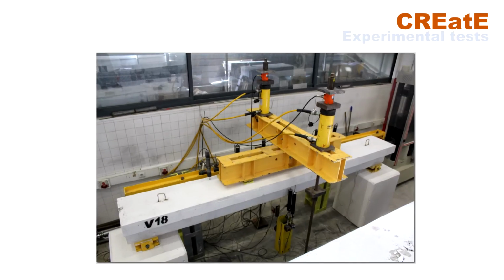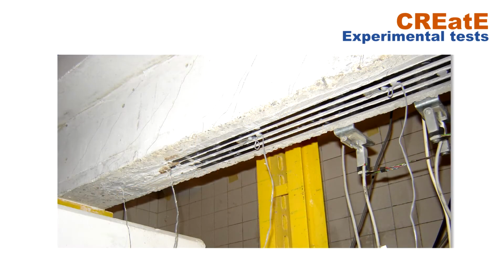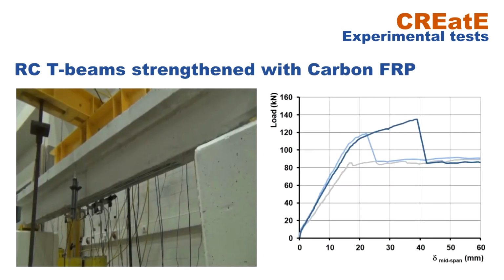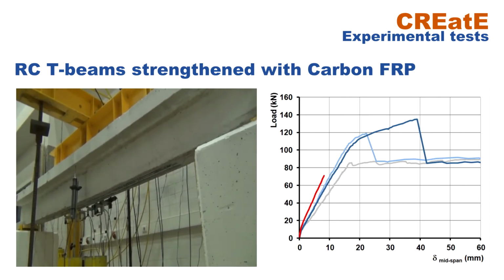The first example refers to the reinforced concrete T-beams retrofitted with carbon FRP laminates using the CREatE system. You can see the video of the test and a graph showing the vertical force applied on the beam versus the vertical displacement. In gray you have the previous test curves of the reference beam. In light blue the test curve of the traditional strengthening solutions, EBR, and in dark blue the NSEM. In red you have the test curve of the CREatE system presented in real time, which is compared with the curves of the reference beam in gray, of the EBR in light blue and of the NSEM in dark blue.